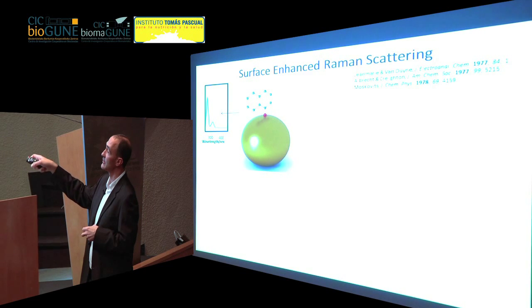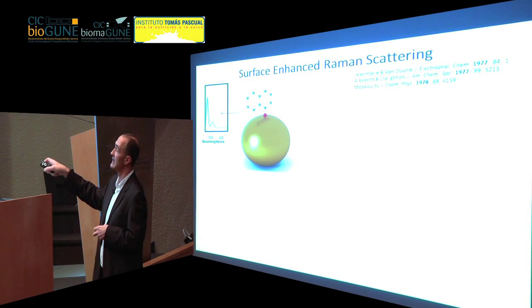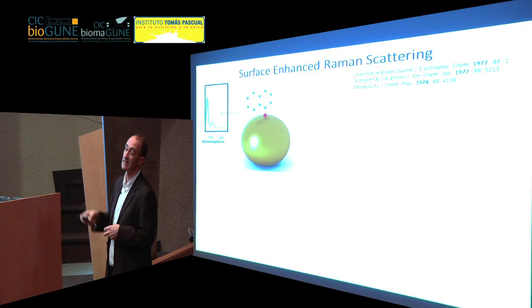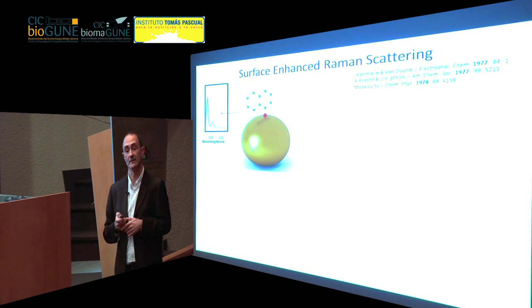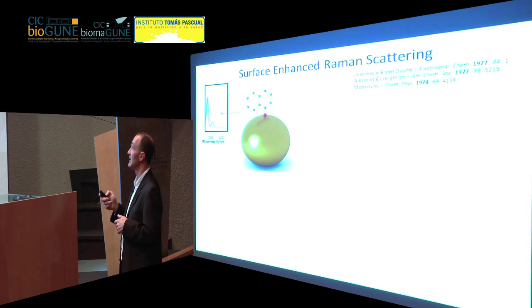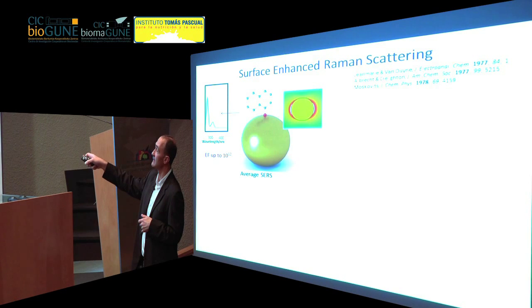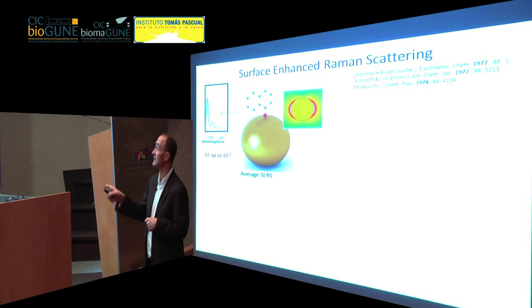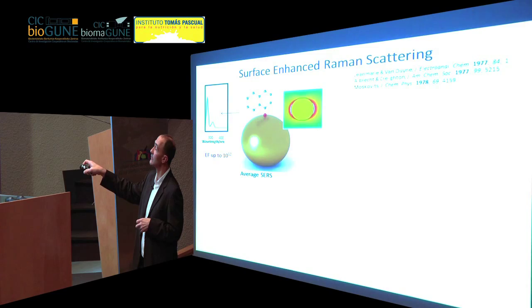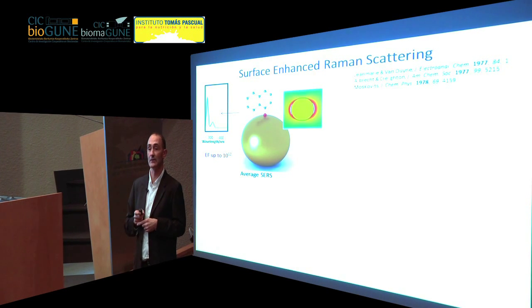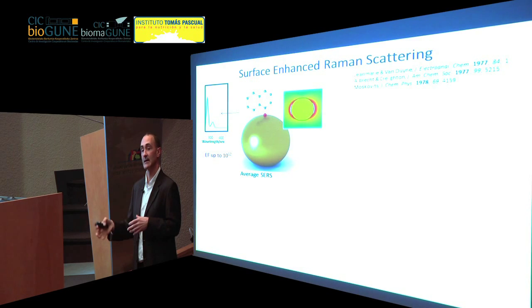You have your molecule, you attach it to the surface of a nanoparticle, and then you can get a specific fingerprint Raman scattering spectrum for this molecule, which gets highly enhanced because of this electric field that you're creating. So in theory, you could get enhancement factors even of 12 orders of magnitude, which means that you can get the same information with a much lower amount of material.